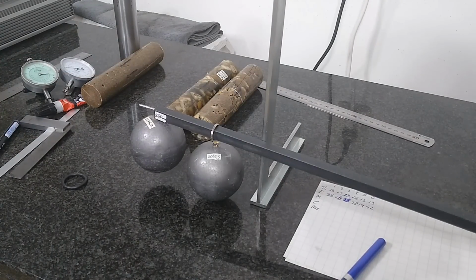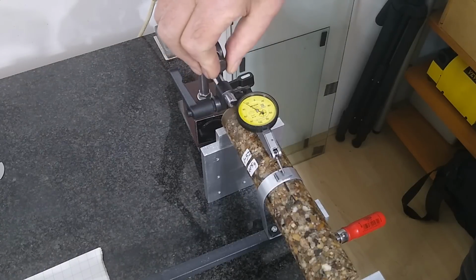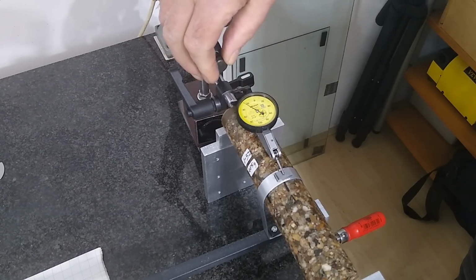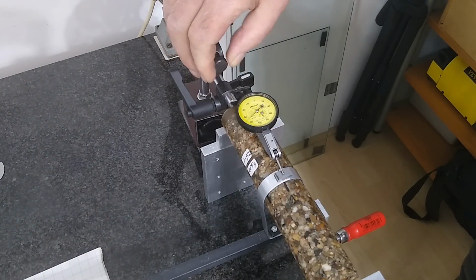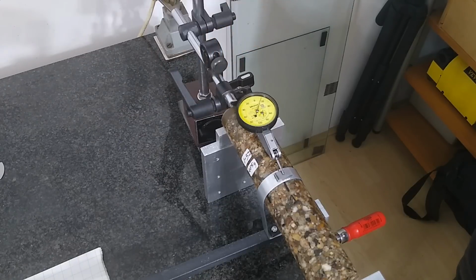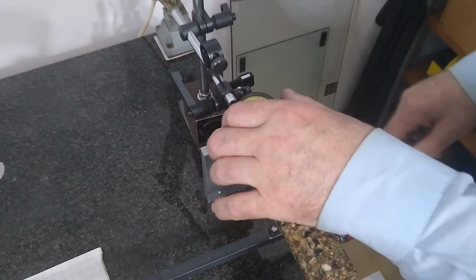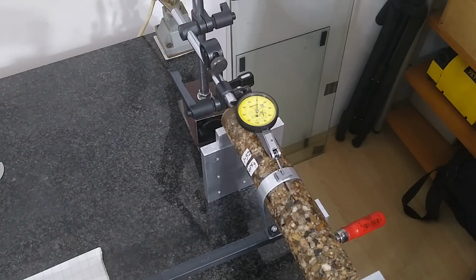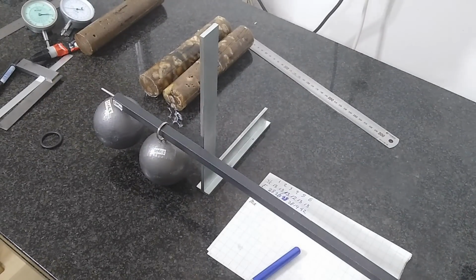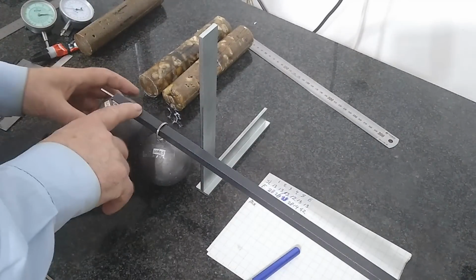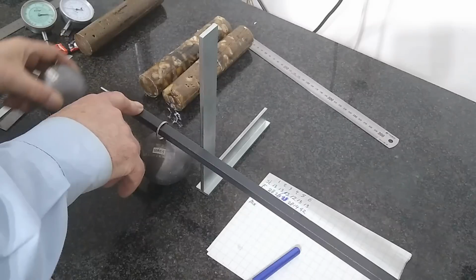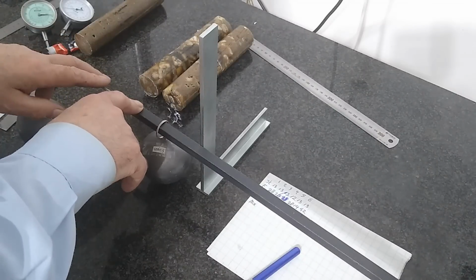This setup gave much better results. Not only is the force now transferred through a large surface area, but I have also switched to applying a preload of 200 newtons, but still the results were not really clear. This was particularly visible with the steel test rod. This is an accurately round and true tube, yet the deflection measurement results varied by as much as 5 microns.